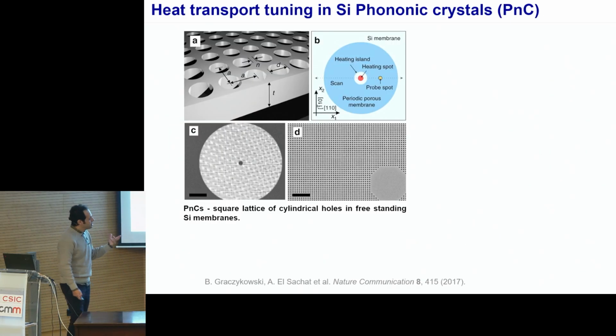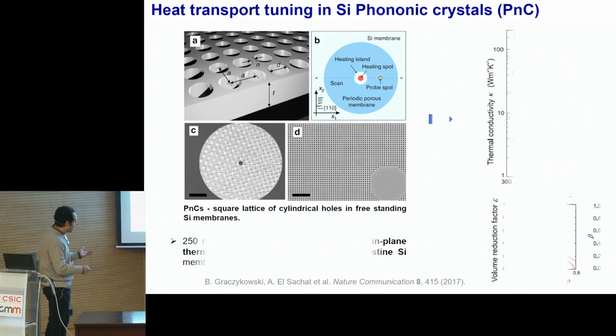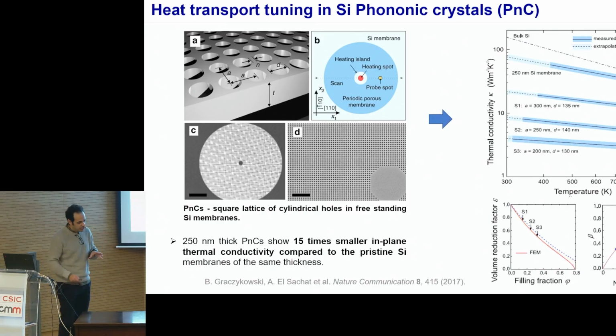But we can do this in a more efficient way by creating phononic crystals in the silicon membranes, and actually we don't have to end up with a membrane thickness of 8 nanometers. We found the same results and even better results in 250 nanometer thick silicon membranes by creating this kind of phononic crystals on top of the silicon membranes. So we were able to again reach very low thermal conductivity values.